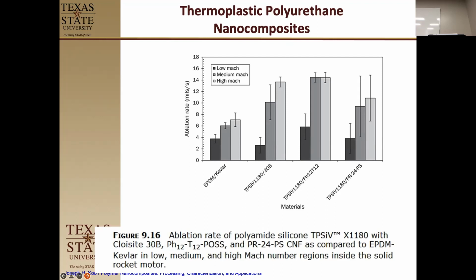Huh. So it did okay at low, when you had lower heat flux. But as you raise the temperature and raise the speed of the gases flowing across it, it did poorly. It's like the soft phase was being pushed or moving. Okay, so then they did it with a different derivative. This is, I want to say, like a POSS type structure here. They saw a similar behavior where the lower speed gave a better number. But their best one was when they added a different type of filler. It's not montmorillonite. They got it to be not so bad. But in all cases, at the higher Mach speed, it performed worse than the stuff they were comparing to.